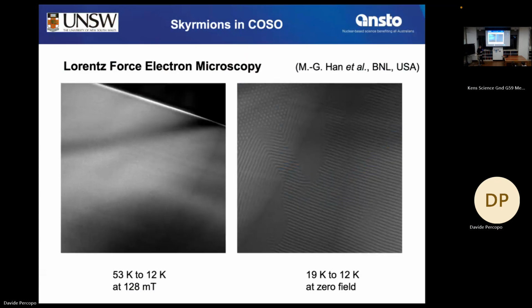So the crystals were grown in New Zealand with my colleague Thilo Söhnel. And we shipped the crystals to our colleagues in Brookhaven National Lab. They have an electron microscope. And they measured these pictures on our samples. So here, the zebra stripe structure, that's actually the helical structure. So you have a spin helix like that, and then the next, and then the next. So top view looks like a zebra stripe.